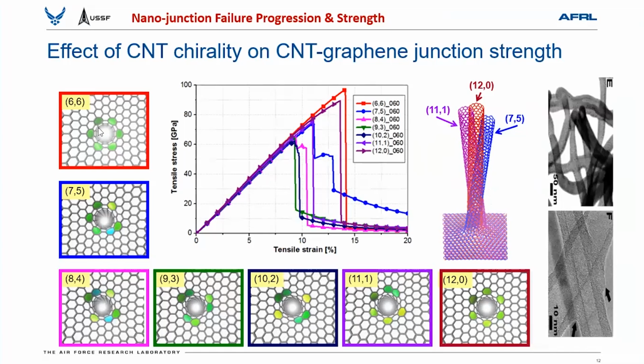As you see, for armchair 6-6, these 7-member defects are regularly, uniformly distributed across the junction area, and that gives us, like in structural mechanics, when your defects are uniformly distributed, a higher strength or load-carrying capability. The same is true here. As you see, when these defects are regularly distributed, we get higher strength as compared to the other irregular distribution. So that's the design area if you want to join graphene to CNT.